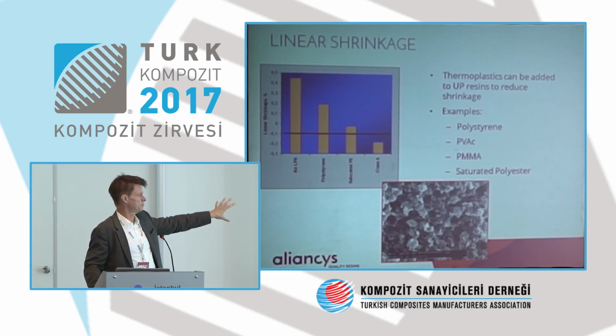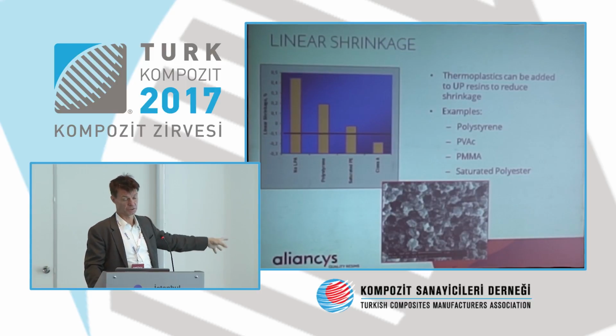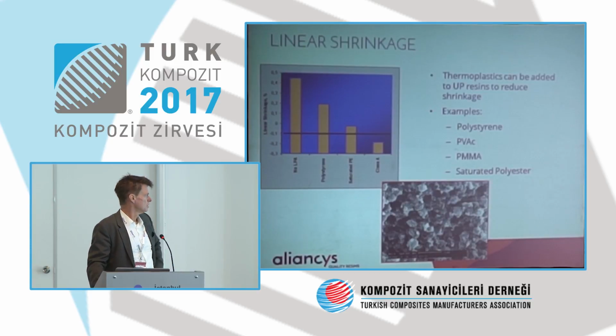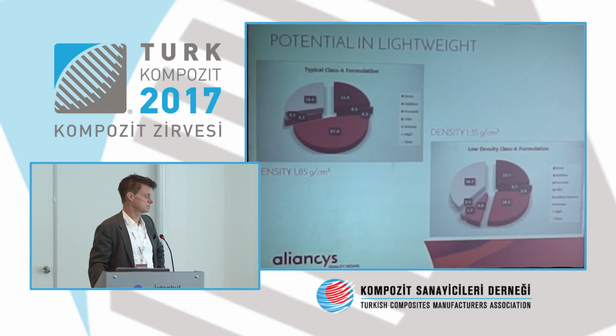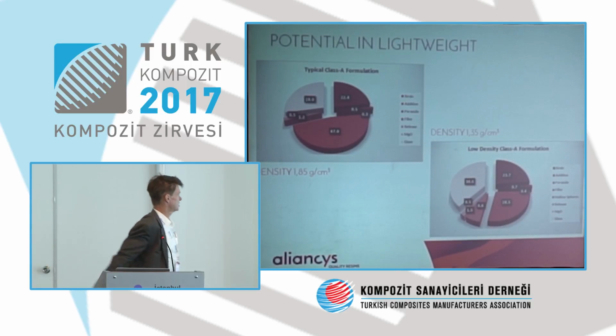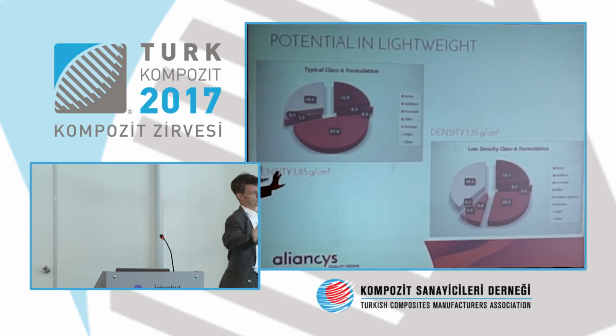So this is about shrinkage compensation, and we have these products. I will come later to the products you can use in order to get there. The second parameter is, we talked about density. So I said, this is a standard density, which is typically used, about 1.85.